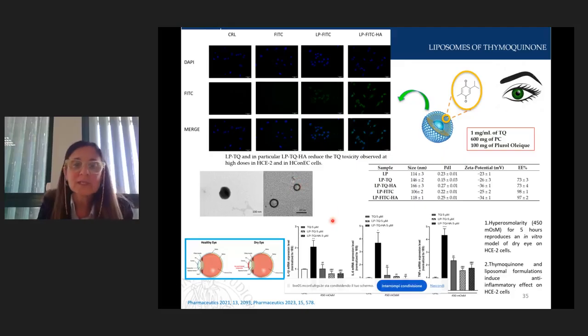These liposomes are also tested in a model of dry eye pathologies. In this case, we observed that thymoquinone, as reported in the literature, reduces the inflammation in the dry eye model, but also the presence of the liposome and of hyaluronic acid around the liposome ameliorates the efficacy of thymoquinone against the inflammation produced in the dry eye.